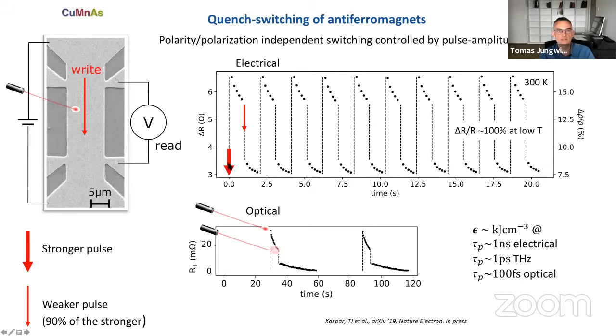So if we deliver a stronger pulse, we have this higher resistivity state. And then if we deliver a weaker electrical pulse, we switch the system into a lower resistivity state. So we can reversibly and reproducibly switch the system between high and low resistivity states by changing the amplitude of the writing pulse. Now, what is striking is that these resistivity changes, again, are in a simple single layer antiferromagnetic film and in a device which is just the simplest 2-point, or if you want, a 4-point resistivity measurement device. We see relative changes at room temperature which reach 20%, and at low temperature changes reaching 100%.